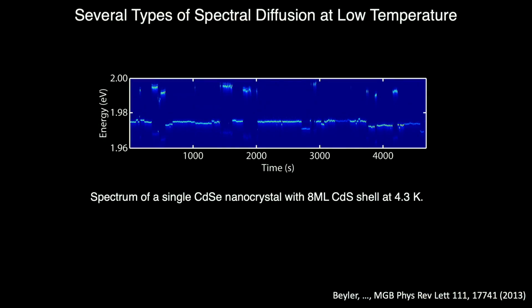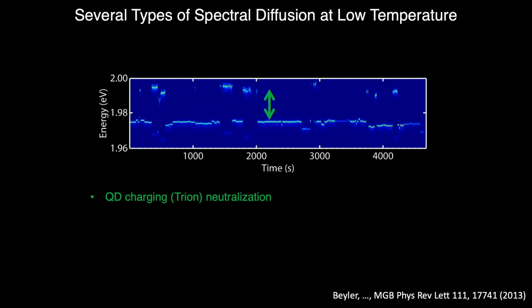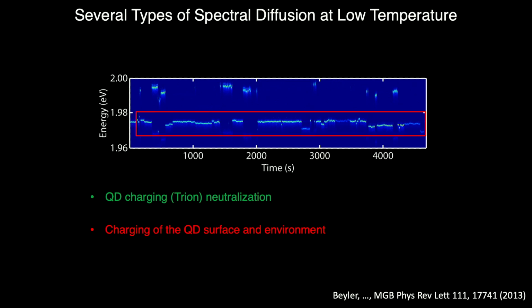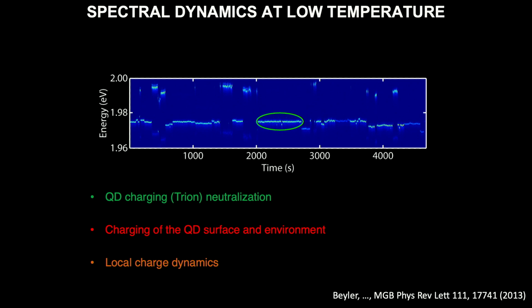For instance, if you take the spectrum energy here as a function of time at low temperature, you find that the energy of that electron emitting a photon jumps around, okay? And we understand what that is. It's because the particles every now and then charge up, so now they have an extra electron in them, and then neutralize, charge up, neutralize. The surface has charges on it, and those charges move around. That creates an electric field, a Stark effect. And so these little motions here are due to the Stark effect of the environment. So we're basically having a sensor of the environment. So we're looking at the local charge dynamics and the charging of the particles.